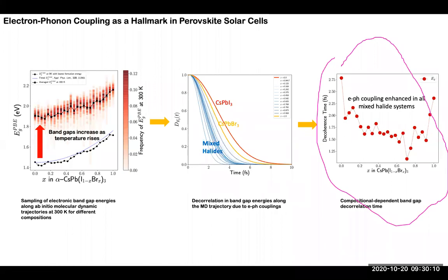No, we have 484, but from memory we have 24 compositions, right? So along X, 24 compositions. For each composition, there will be a lowest energy one, right? So you just take the lowest energy structure and then you run the electron structure calculation, to see how the electron phonon coupling changes at that lowest energy structure. We didn't do that for all 484 structures. That would be computationally too costly. I see.